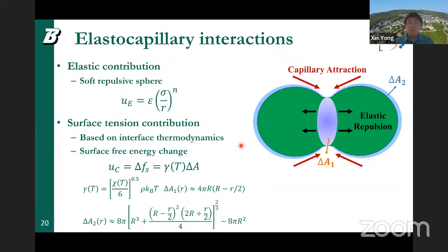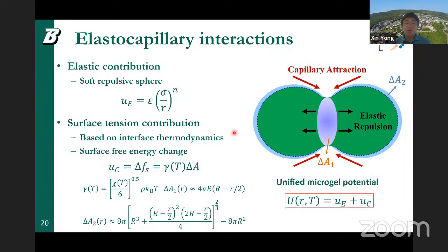And so we try to come up with a theoretical model to describe this potential calculated in the simulation. We combine the two important contributions to this interaction. One is the elastic contribution, which is due to the deformation of the spherical microgel, and that should be pure repulsion. Then there is the surface tension contribution, which is due to the interfacial tension between the microgel and the solvent, which is higher when the microgel is collapsed. So we developed the interfacial thermodynamics calculation by looking at the surface free energy change. This depends on the temperature-dependent surface tension multiplied by the area change due to the merging. So the total potential is unified from these two contributions.